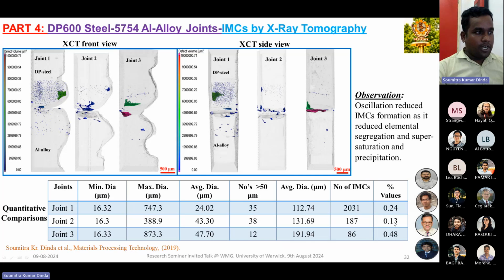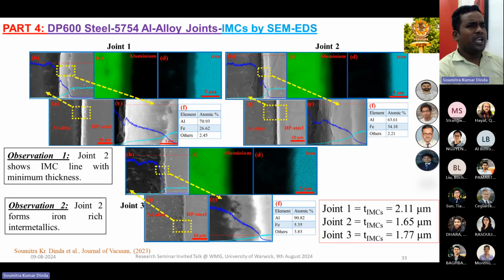That means by oscillating beam, it goes to half. But if you increase the oscillation from 1 millimeter to 2 millimeter, it goes to double, from 0.24 to 0.48. So it does not mean that if you use the oscillating beam, we are getting superior property. That means we have to optimize the beam diameter also. So let's do the SEM study.